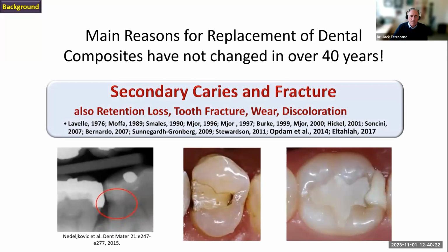And what has been found and shown in the literature is that the primary place where composites, especially class 2 composites, fail is along the gingival margin area. And it makes sense. It's a logical place because it's a difficult place to place the restoration and also difficult to keep clean. And we wonder, is this a problem with bonding? Is it placement or is it actually bonding?